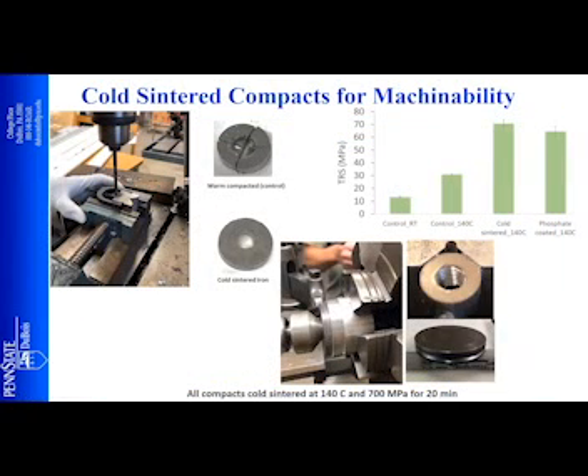Now, in the case of machinability, we have seen that we can even machine the part. We can drill, we can make threads. If you compare a cold sintered part, which is what we call a green part, a drilled green part compared to a warm compacted part, you see that the green parts usually have much higher strength. It is intact after drilling, compared to a warm compacted part. We can even do threading of the parts. The green strength of a cold sintered part is double what you find in a warm compacted part. So that gives you several opportunities which you can use in the green parts, even before you sinter the parts. The opportunities are diverse.